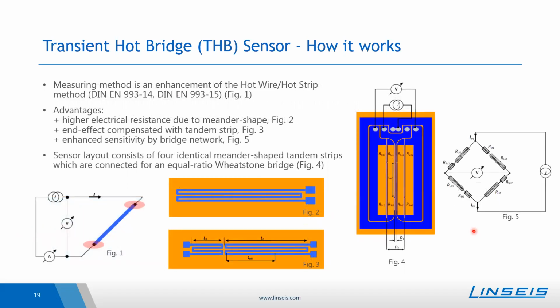Here on this slide, you can see especially the working principle of our THB sensor. As already mentioned, it is based on the hot wire or hot strip method, but the THB sensor is an enhancement of it. Because the hot wire is not just a straight line as one strip, but meander-shaped and also separated into 2 parts with 4 of them connected to a Wheatstone bridge. We have a higher electrical resistance, compensate the end effects, and enhance the sensitivity compared to this basic hot wire setup. Because of that, the accuracy of the THB sensor is also higher compared to the basic hot wire method.